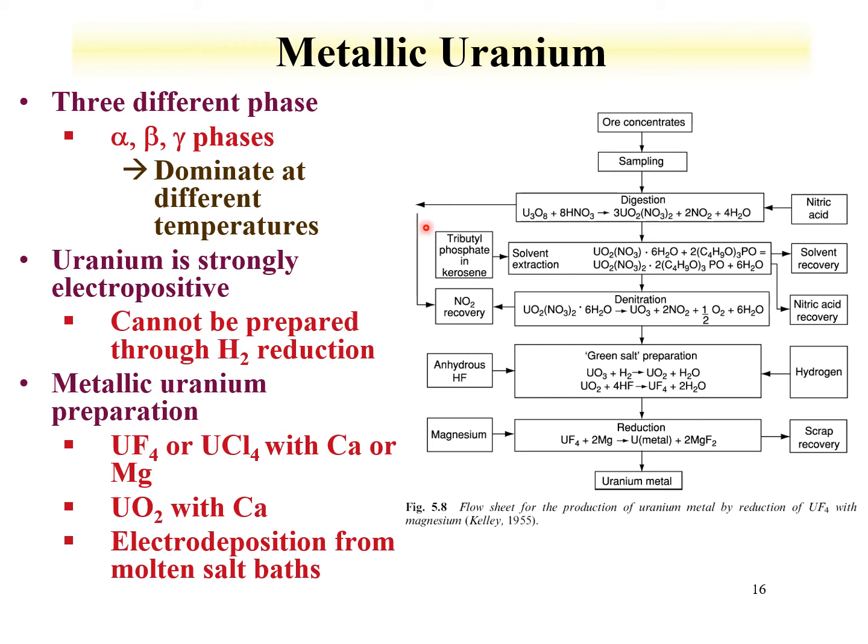So that means to prepare uranium metal, I have to use a different route, and what's done is we make fluorides of uranium. We take those fluorides, treat them with magnesium metal, so a divalent metal or even a monovalent metal would be sufficient to reduce uranium from the +4 to the metal state.